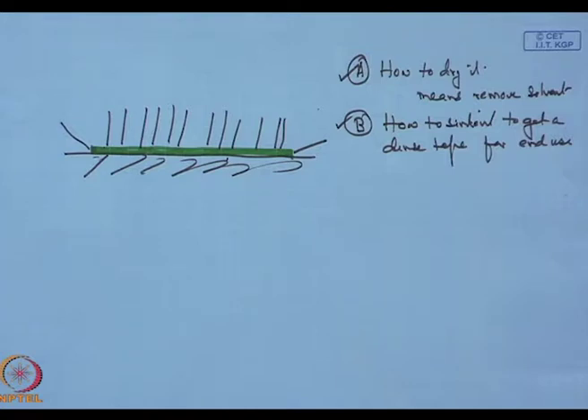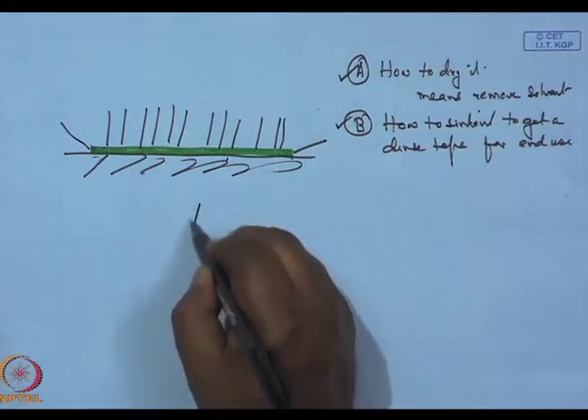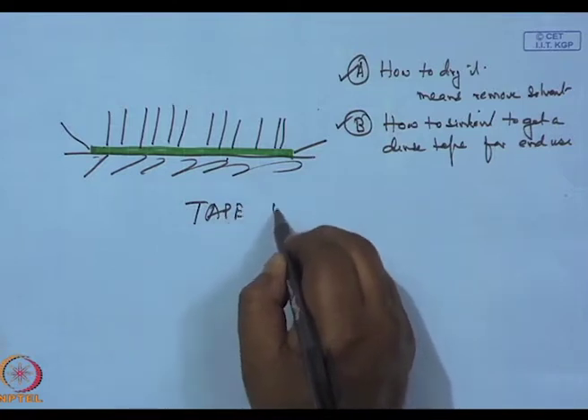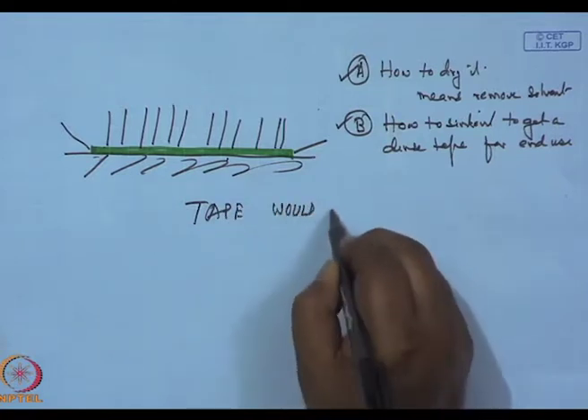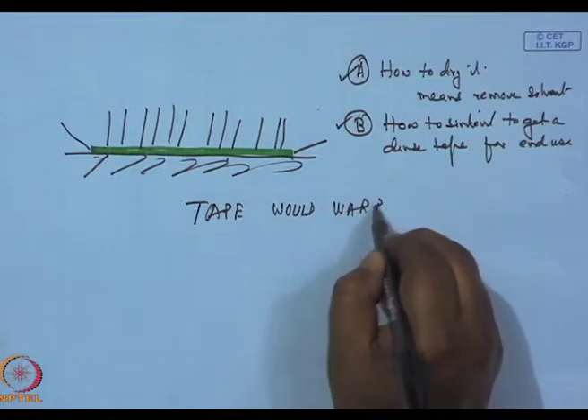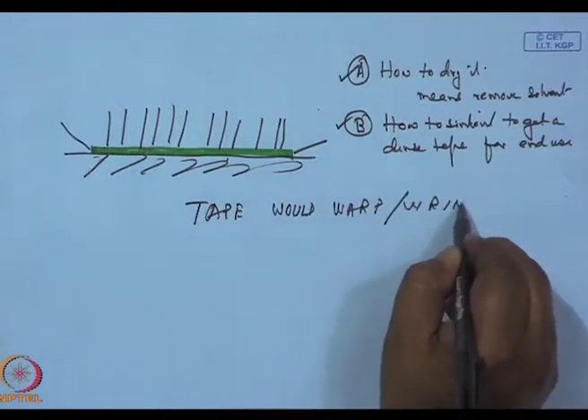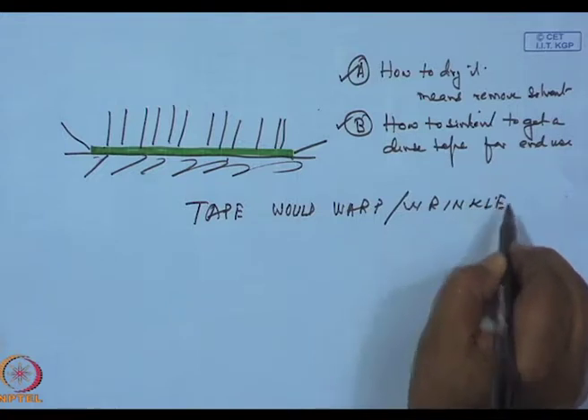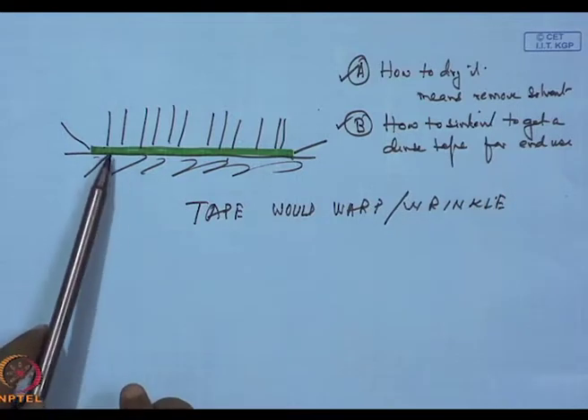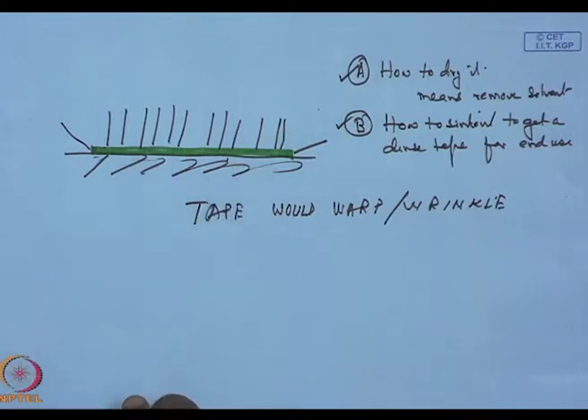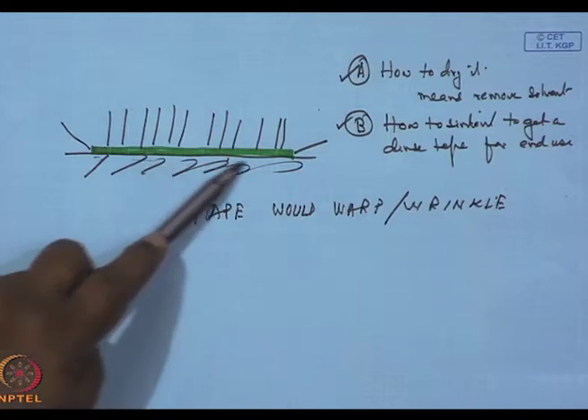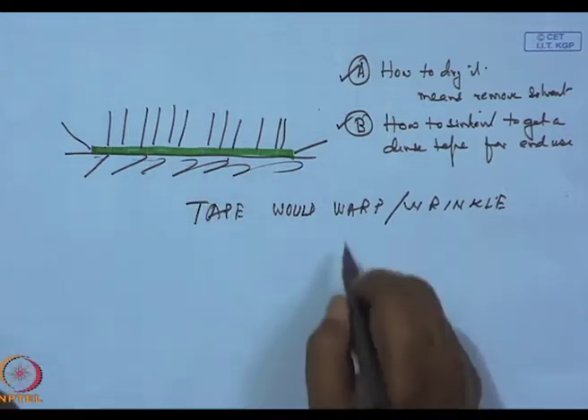So, what would immediately happen if I let this unequal evaporation to go through? The tape would warp, wrinkle, because when the liquid goes away from the top surface it will contract due to surface tension. The liquid is going away while there is plenty of liquid at the bottom, so it would warp or wrinkle.